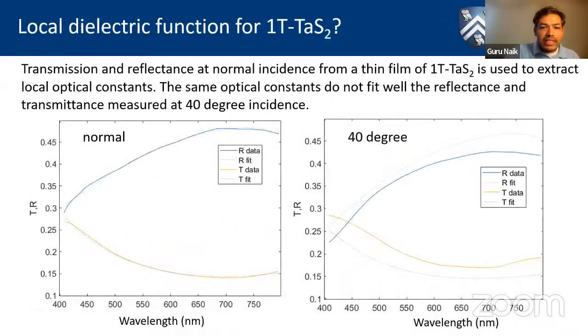But what happens is, as we change the angle of incidence from normal, let's say at normal it fits really well. Then for the same optical constants, if we find out what to expect at a 40-degree angle of incidence, we don't see a good agreement between experiments and theory. So it's really difficult to find one local optical constant that fits really well for all angles of incidence. And that's where we think the local dielectric function is not the right model for our material.